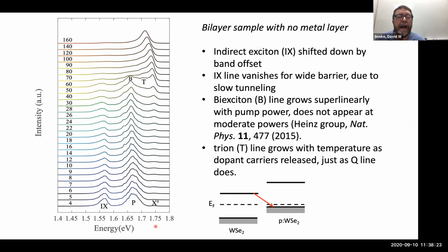Just a couple of points. One is that the line isn't there. This is the sample without the metal layer, and the Q line doesn't appear, okay? The other is that when we do the power dependence, the Q line scales linearly with the exciton. It's not going as the square of the exciton, so it's not fitting the expected power dependence for the bi-exciton.